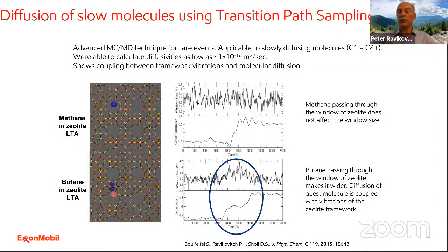As you can see, butane gets stuck in the window for quite some time. And if you look at the window size as a function of simulation time, it actually expands quite substantially. It doesn't happen for methane, but it does happen for butane. So this is very important. This coupling means that you can no longer expect a method like the snapshot method I just showed you to work, because now you need to take into account the coupling.